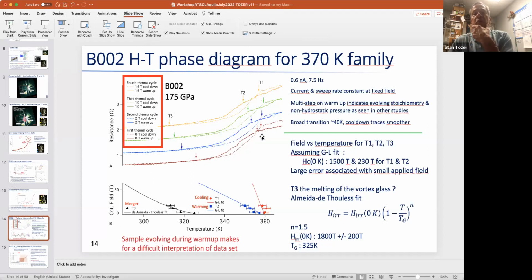But interestingly enough, something that needs to be pointed out in these traces here is, as we warm up, that's when we're starting to evolve more hydrogen, we believe, and also possibly introducing more material into the lanthanum hydride other than hydrogen. You can see there's a multi-phase composition here, but as we cool down, it smooths out. And in fact, each time we go up, this was the first trace, 0T, and then we went up to 2T, 10T, and then 16T. Each time we go through and up to max temperature, things start to smooth out.